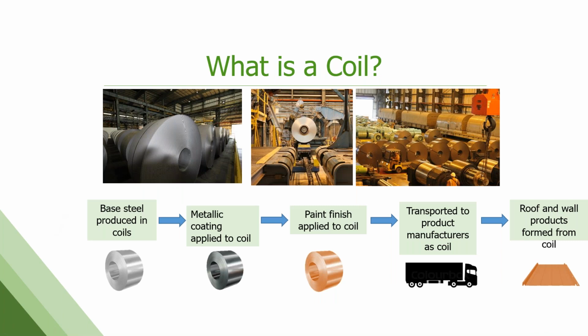So take a step back real quick. The product we're talking about is all coil product or flat rolled steel product. For those who aren't familiar, here's some pictures and a little bit of what the process looks like. So we start with flat rolled steel, uncoated steel. It's either called hot band or hot roll typically. We then reduce that down to its final thickness and width that it needs to be for the final product, after which then we apply this metallic coating to it. And that's a continuous process. If it's going to be painted, it then moves to a continuous paint line to get painted, and then is shipped out in coil or roll form to the fabricators who are going to make wall or roof panels out of it.